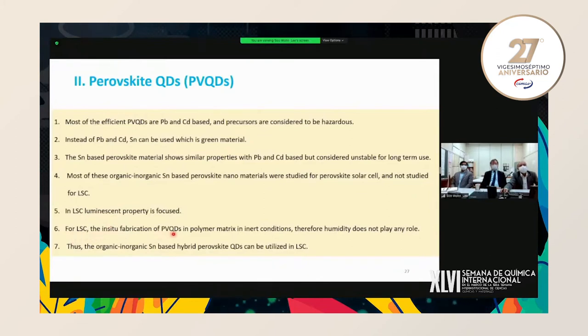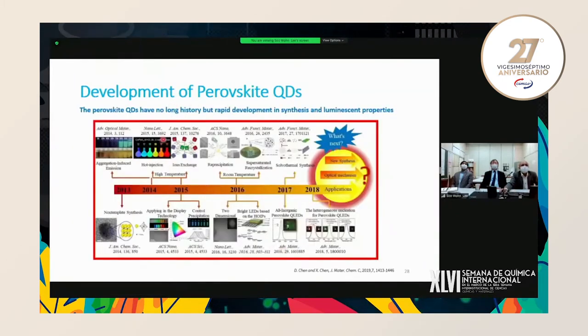For LSC, the in-situ fabrication of perovskite quantum dots in polymer matrix is done in inert conditions. Therefore, humidity does not play any role, and there will be no problem for the stability. Thus, the organic, inorganic, tin-based hybrid perovskite quantum dots can be utilized in LSC. So here, the perovskite quantum dots have no long history, but rapid development in synthesis and luminescence properties. Here we can see the perovskite quantum dots are fabricated by different methods like aggregation-induced emission, hot injection, ion exchange, reprecipitation, supersaturated recrystallization, solvothermal synthesis, non-template synthesis. And these are applied in different fields like display technology or quantum LEDs, also in perovskite solar cells.